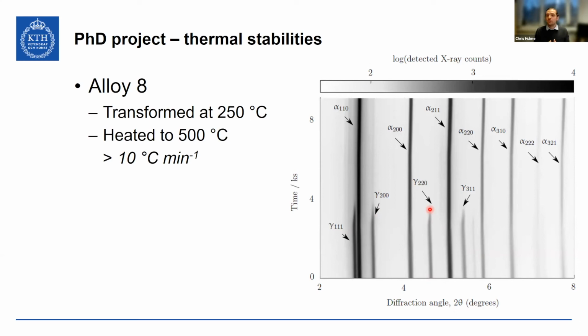And shortly after that, the austenite disappears. So this is thermal decomposition of the austenite exactly as it's been reported in literature. So basically, alloy 8 didn't work for what we wanted it to do.